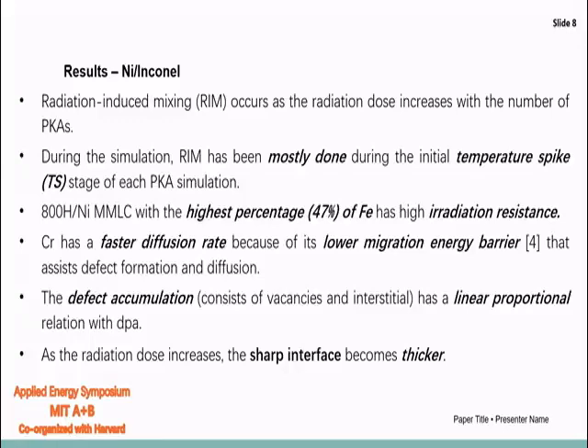We can see the chromium has a very low migration barrier, so it has a very high tendency to accumulate defects and thereby create the diffusion. The presence of the defects also lowers the migration barrier for nickel, and that enables the nickel to diffuse faster and create some defects. Also, the defect accumulation and the thickness of the interface have a very linear relation with the radiation dose. We can also see from our very initial image that the sharp interface of the nickel-Inconel heterostructure gets thicker when we introduce the primary knock-on atom and increase the radiation dose.